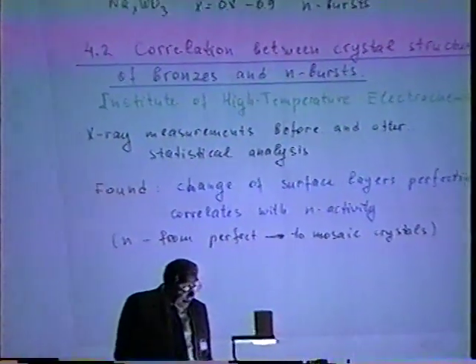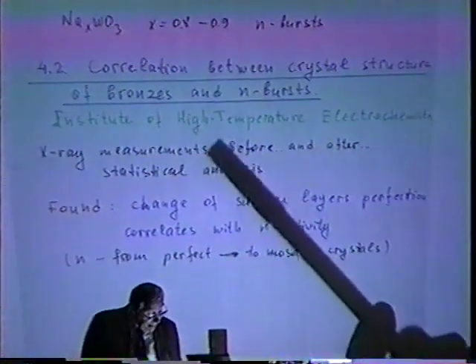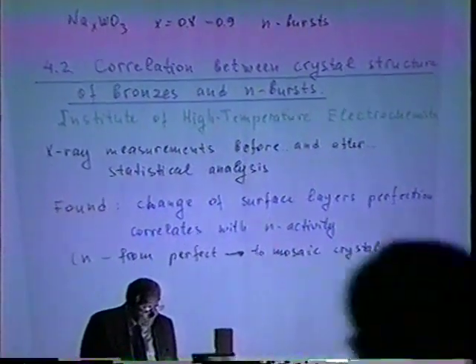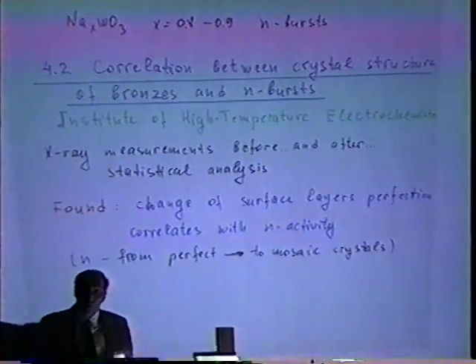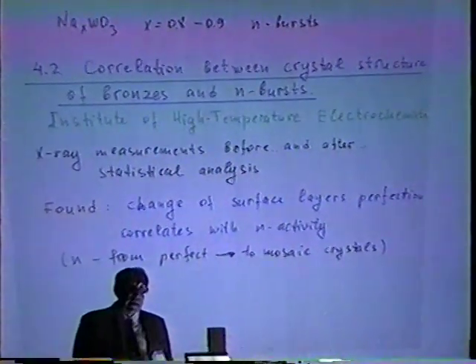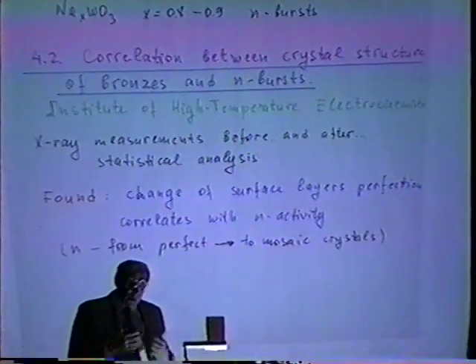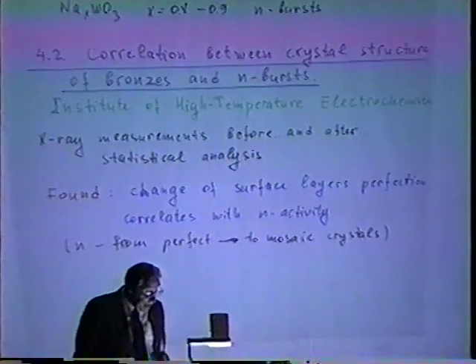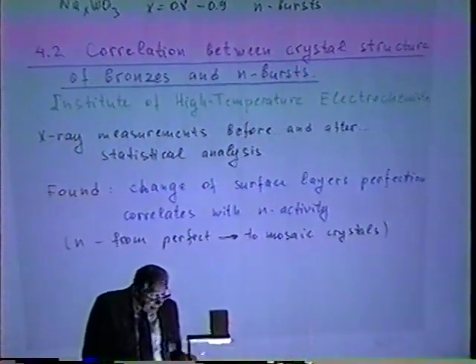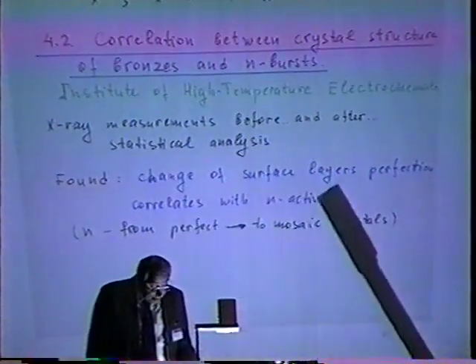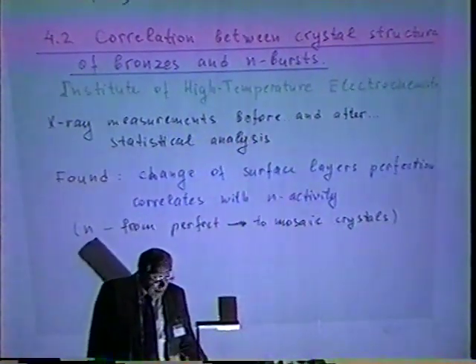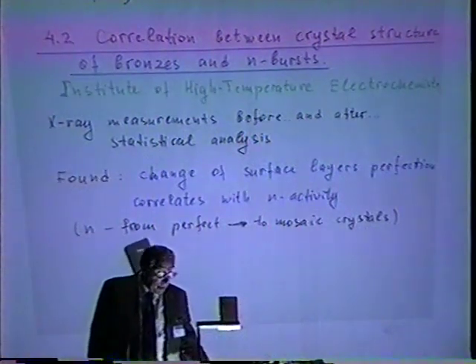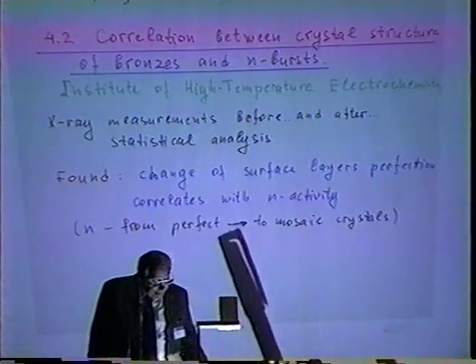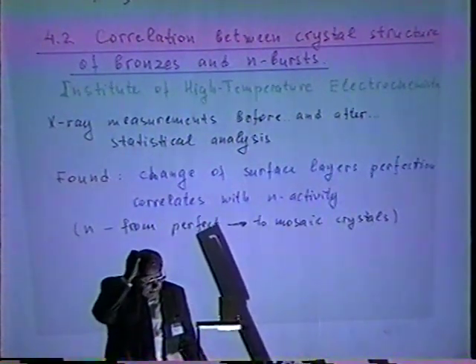The work with the same material is also going on in the Institute of High-Temperature Electrochemistry. They try to understand whether there is any difference in the structure of these crystals in the case when they produce neutrons and in the case when they don't. And they really observe that there is a correlation. Their statement is the following: there are some changes in surface layer perfection correlated with neutron activity. Neutrons are produced in those samples which had some transition from a perfect near-surface layer to a mosaic crystalline structure.